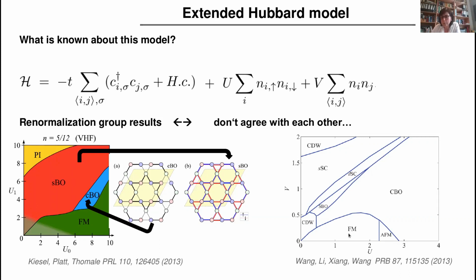Now, this is a work done also with the same method. However, the phase diagrams don't agree with each other. If you look at them, ferromagnetism as a function of U dies out here, and then there's a region of antiferromagnetism which is not present in the other diagram, even though here the values are larger. The different phases that appear as a function of V seem not to agree with the phases in this phase diagram. So for us, it was a starting point to say, why don't we first try to understand this phase diagram, and then we will go to the material.